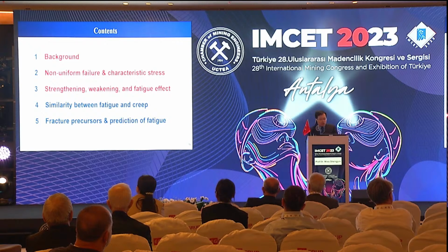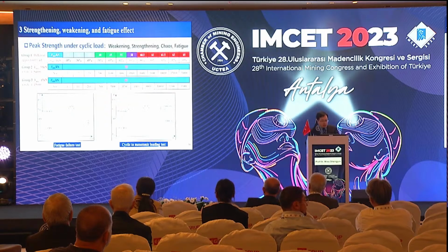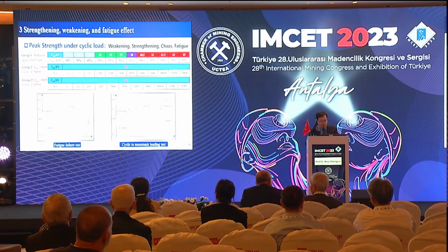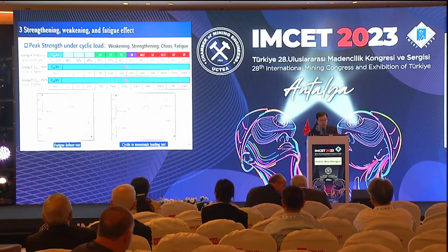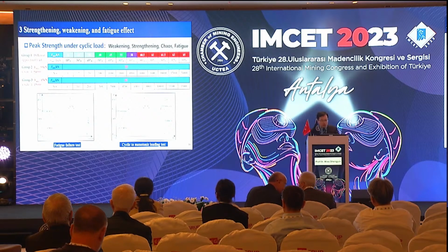Part 3, strengthening, weakening, and fatigue effect of rock under cyclic loads. In this part, based on the previous characteristic stress division, we studied the influence of upper limit load and cycle numbers on the mechanical properties of siltstone. First, as shown in test group 1, cyclic load tests were conducted at different upper limit loads. If the specimen failed during the cyclic loading process, it was called a fatigue test.